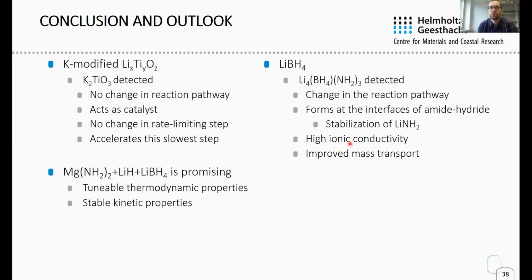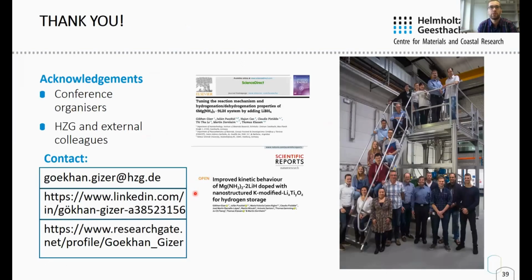Comparing these two systems, the system with lithium borohydride is interesting since we can tune the thermodynamic properties by changing the amount of lithium borohydride. Moreover, it has very stable kinetics over cycling. This is a big advantage for real applications.